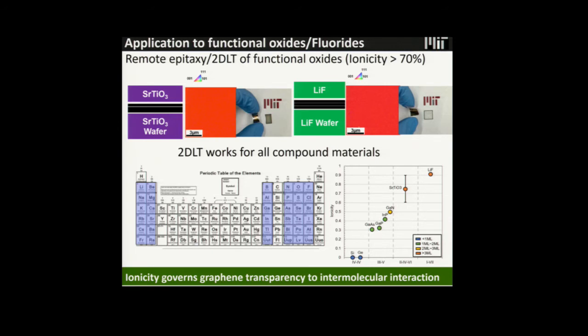Of course, so far there's no concrete way to peel off the functional oxide, even though it's supposed to be really useful, because with functional oxide, if you apply strain, there is so much interesting physics to be found. But there's no way to have a freestanding functional oxide. Functional oxide means an almost completely ionic bonded material. That way, with tri-layer graphene through STO and lithium fluoride, all these functional oxides, we can still have a single crystalline functional oxide, and we can peel it off, then we can have a flexible functional oxide here. So the conclusion: ionicity governs graphene transparency to the intermolecular interaction.